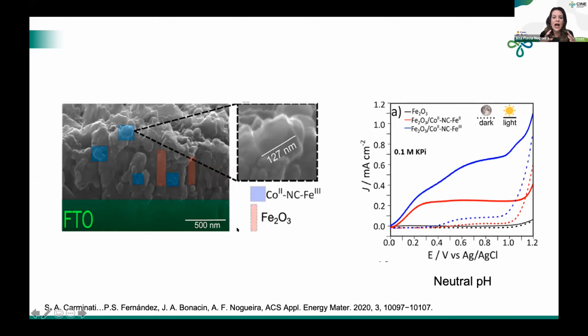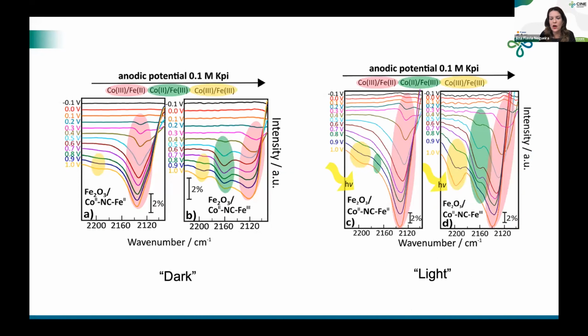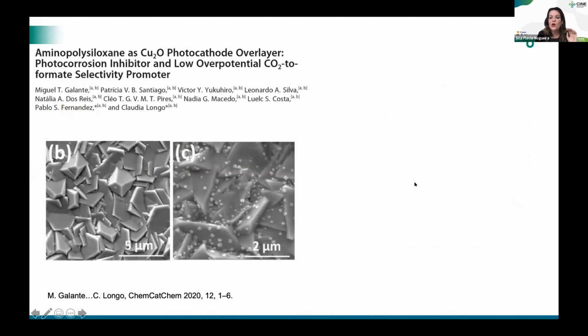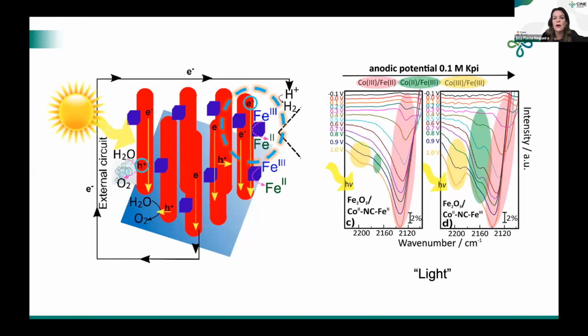But then it's such a mixture of different oxidation states that it was only possible to understand the mechanism using this technique. Of course, I'm not going to have time to go into details, but I just want to show you. One minute? One minute, okay. I'm finishing. I'm just going to show here the difference. Here is the evolution of the infrared when you apply a voltage. You can see here the appearance of some bands, but when you compare the dark and the light, you can see that it's really different. And then with that, we propose the mechanism for oxygen evolution using this material.